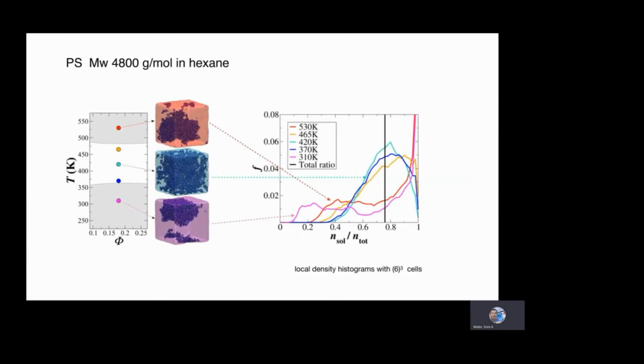Without any general fitting, we looked at small molecular weight polystyrenes in hexane. In this particular case, this mixture produces both an upper and a lower critical solution temperature, meaning that at high temperatures and/or low temperatures, we see a phase split, while in the intermediate temperatures, we have a homogeneous mixture.